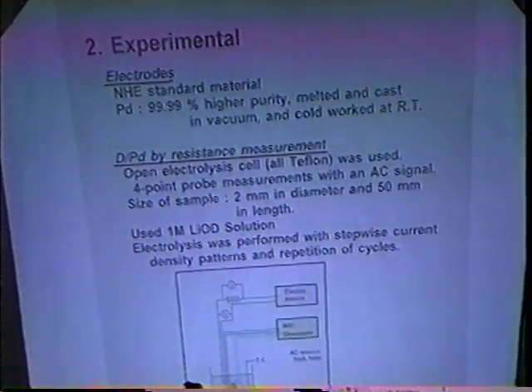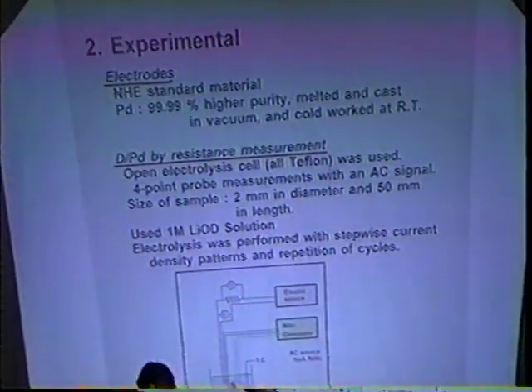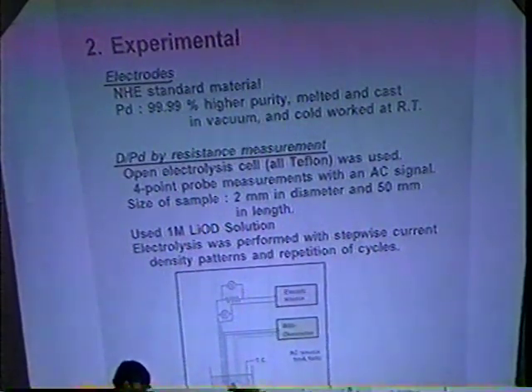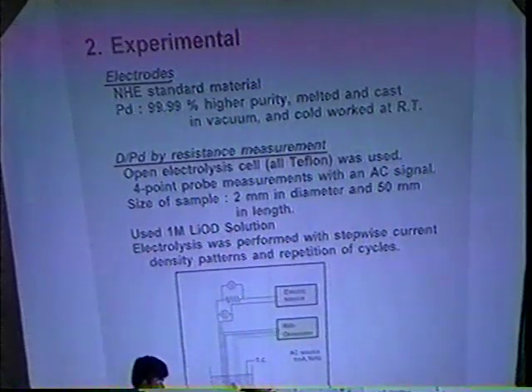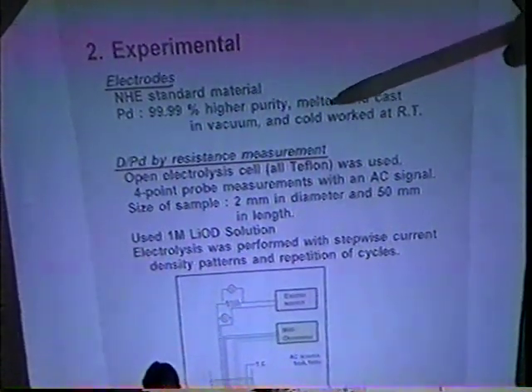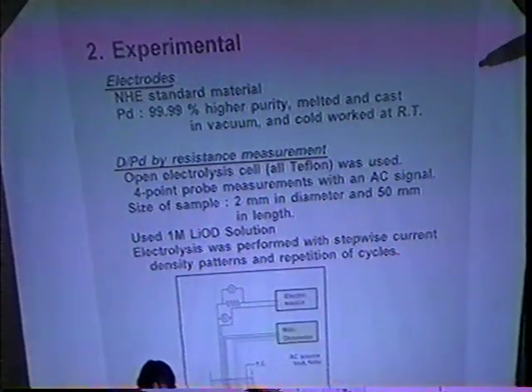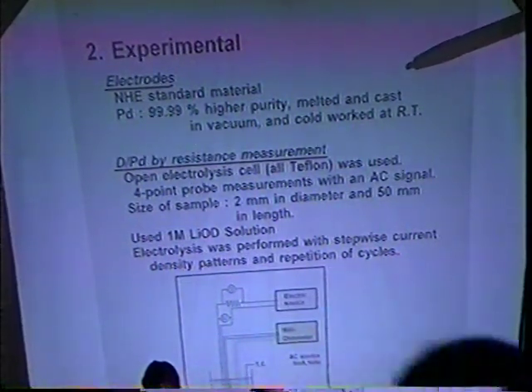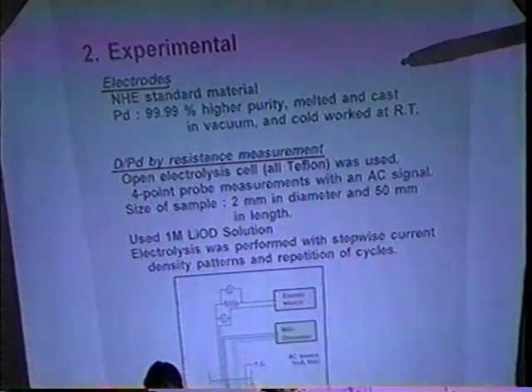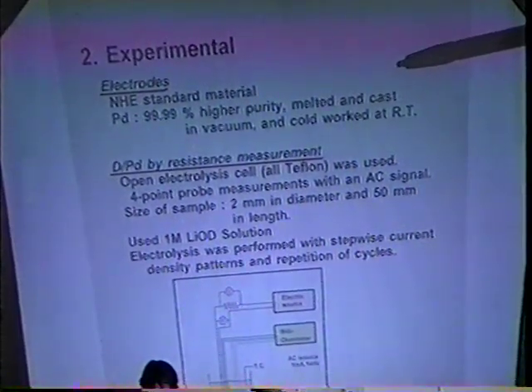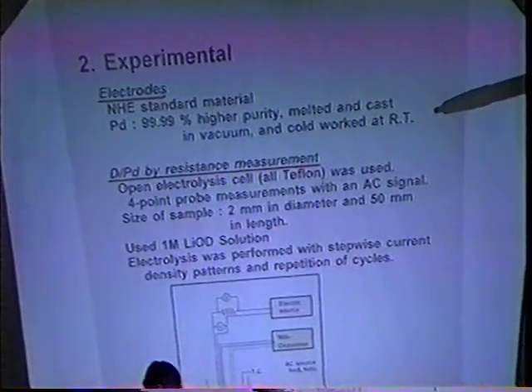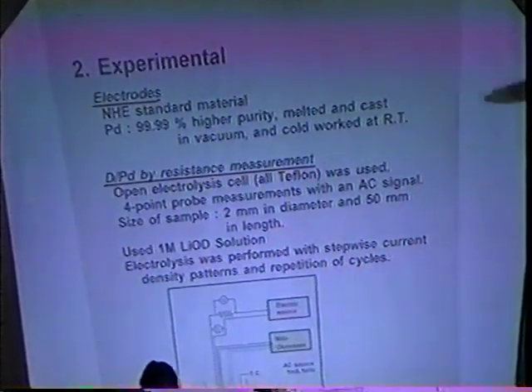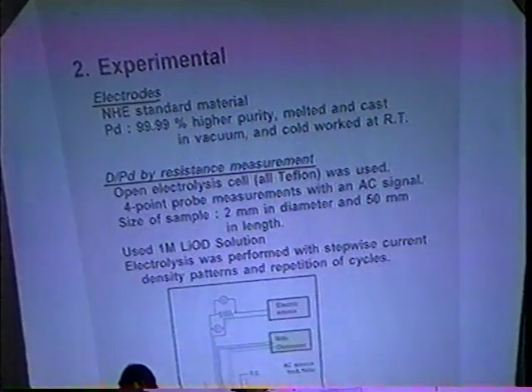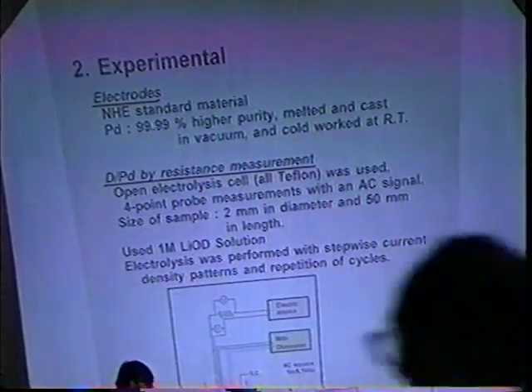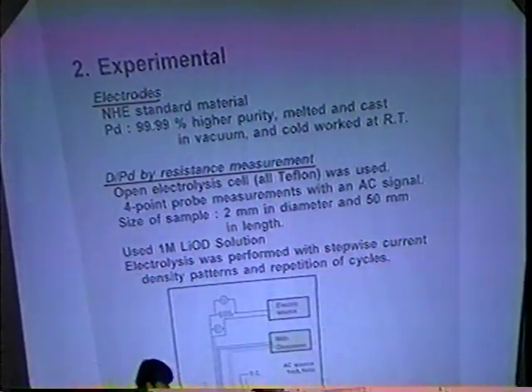For this study, most of the electrodes we used were NHE standard palladium. We start with 99.99% purity palladium, which was melted and cast in vacuum, and cold worked at room temperature. This process will be described by Dr. Alasami after this presentation.